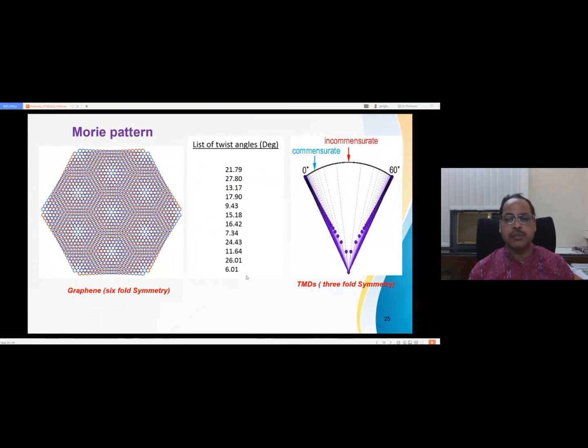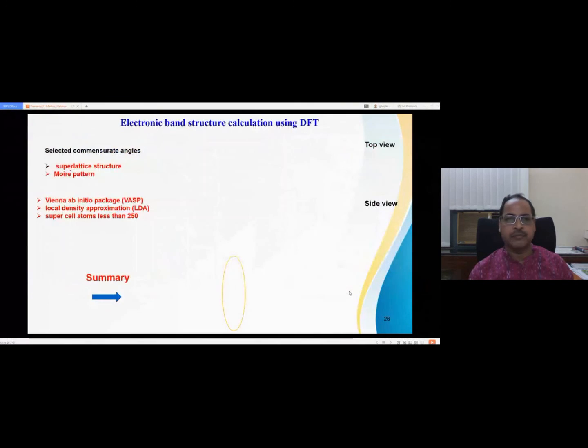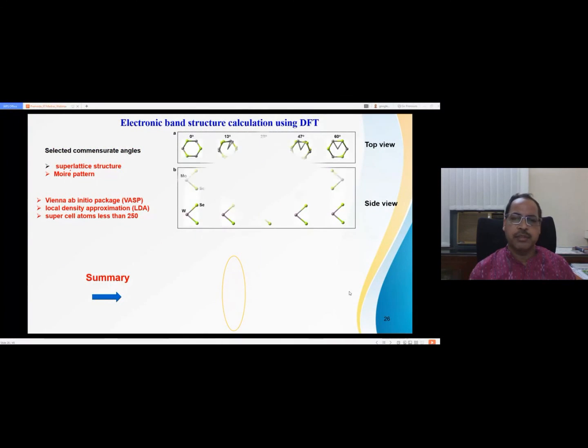So these are all the possible twist angles in the case of graphene. In the case of TMD, you can also go to particular commensurate angles and get the Moire pattern. So you cannot calculate the electronic band structure at every angle. When there is a commensurate structure, you get the Moire pattern, and at that particular angle you can also create the superlattice and calculate the band structure. This is from 0 to 60 degree. This is TMD, which has 3-fold symmetry. So now we have done the DFT calculation with the help of our theoretical colleague.